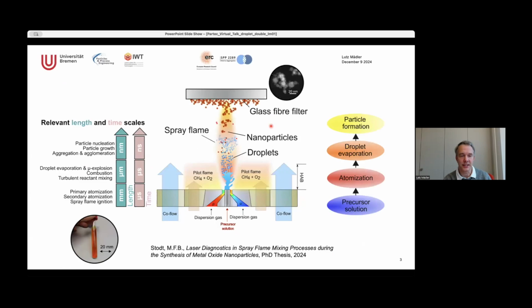Yeah, maybe I go here. As I said, this is a picture by Malte. Malte did his PhD with Udo Fritsching here from Bremen. This is basically a flame that runs with oxygen. Anytime you have oxygen and a metal component, you most of the time make metal oxides. But recently we were able to show that we can also make sulfides. Sulfides can be made in two ways. Instead of the oxygen, you can have some kind of sulfur source in the gas phase. We're working here on H2S. The other way is to put the sulfur source directly into the liquid. Then you have to make sure that you still have enough oxygen to drive the combustion, but not enough to get oxides, while having enough sulfur to get sulfides. And this has been a breakthrough in the last couple of years, to have really nanocrystalline sulfides.